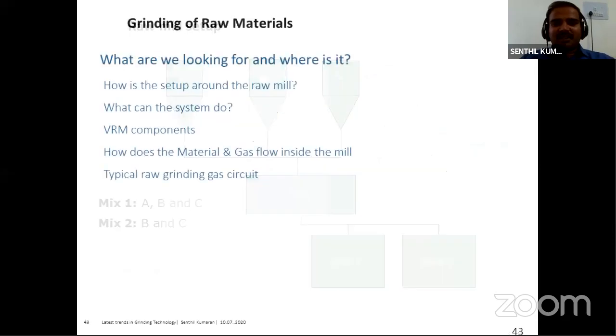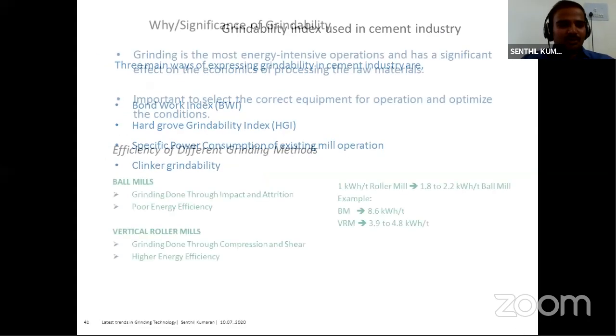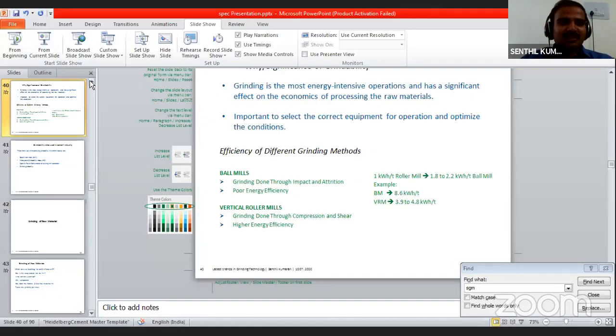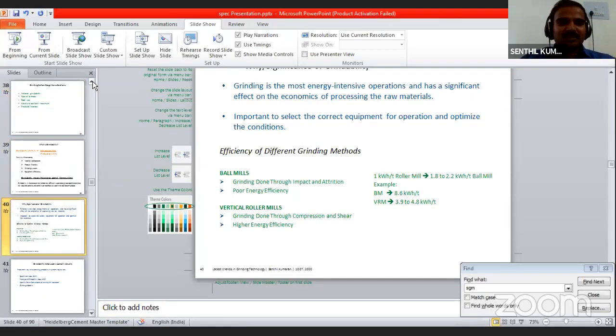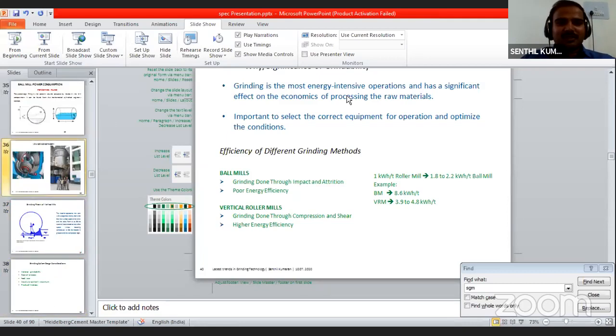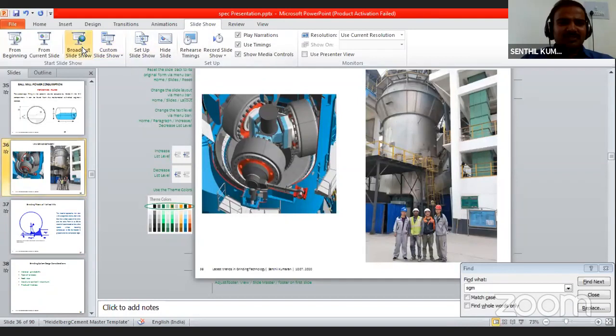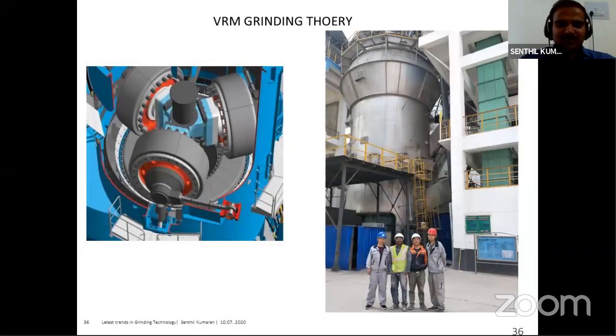So the centerless grinding is normally called central drive grinding. Typically the old type mills were driven by a girth gear, and through the girth gear the mill rotates. Recently, or not so recent, at least 15 to 20 years old, the mill has a center shaft, and then there is a gearbox, and the motor is connected to it, and then it is rotated.